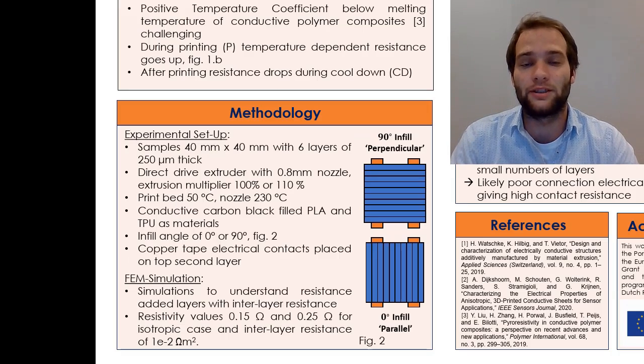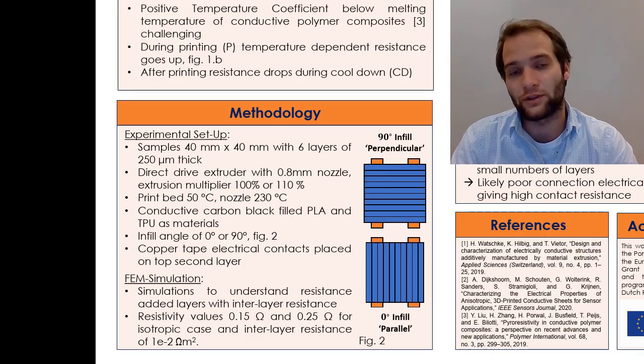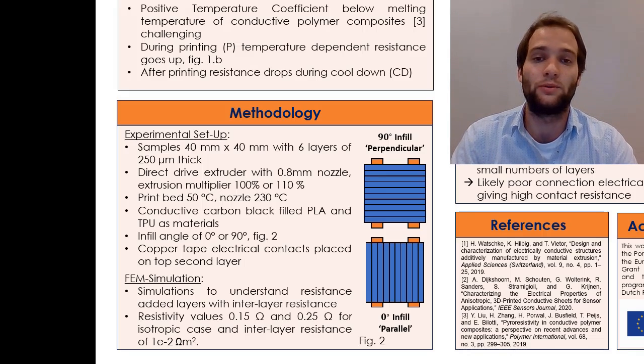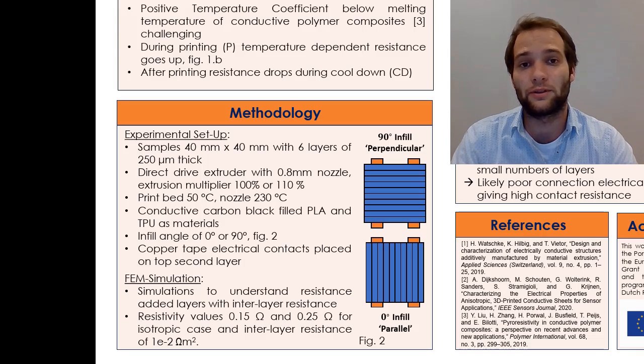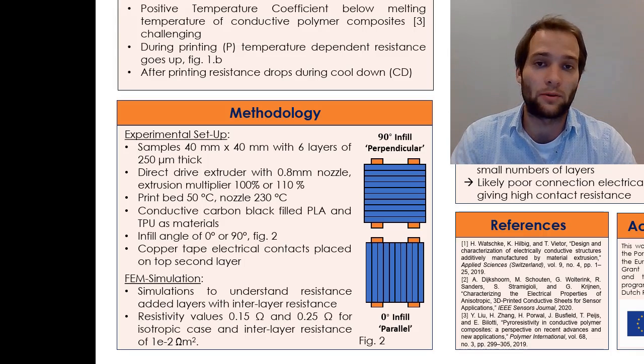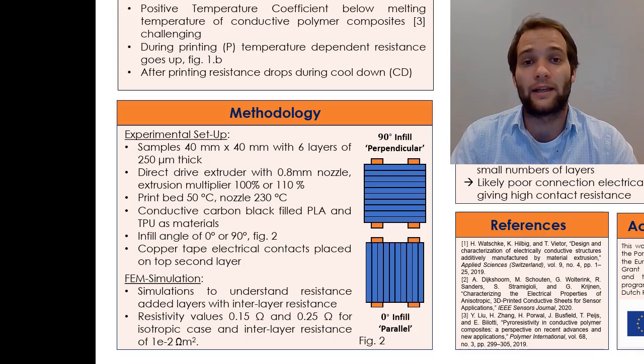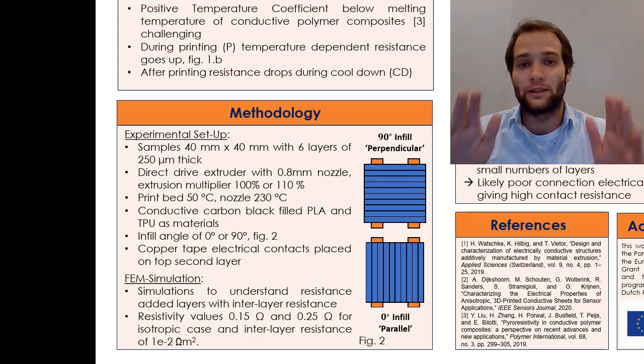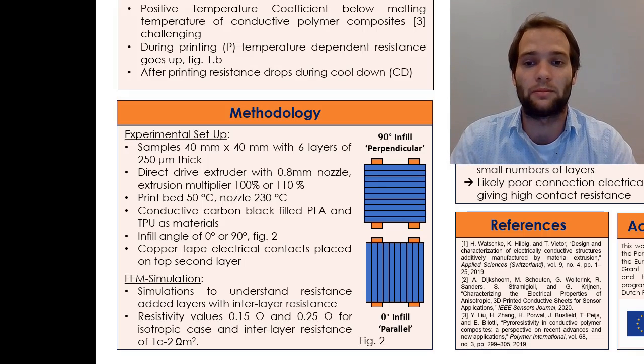For the methodology, we printed small samples of 4 by 4 centimeters with 6 layers, where every layer is 1/4 of a millimeter thick. We've used a direct drive extruder to print both conductive PLA and conductive TPU, thermoplastic polyurethane filaments, which are filled with conductive carbon black particles. As electrodes, we use copper tape, 2 pieces of parallel copper tape on the sample or in the bed.